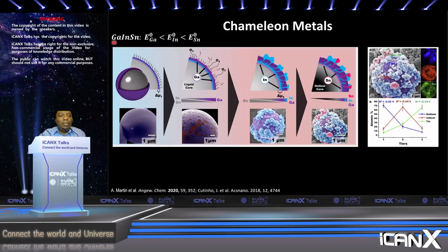And here we took gallium, indium, and tin. Here, gallium has the lowest E0, so it's going to oxidize very rapidly and dominate the surface. But then indium is likely going to be the second one, and then tin is going to be the last one. And our hypothesis was, can we actually release these in sequence? That we have gallium first, then we get a tier of indium, then we get a tier of tin. And actually, that hypothesis again turned out to be exactly as hypothesized.